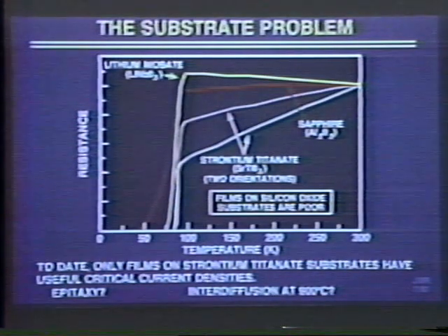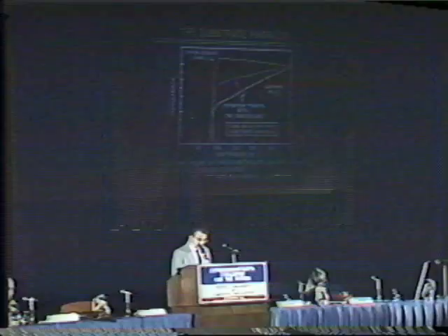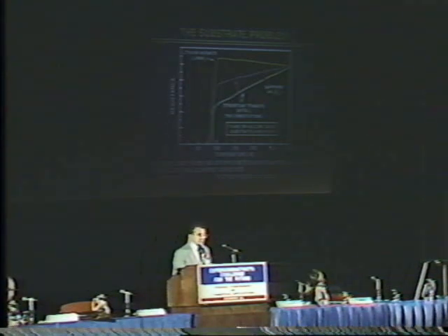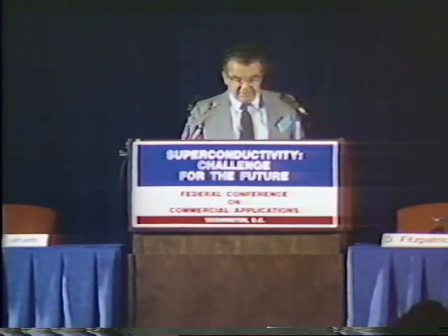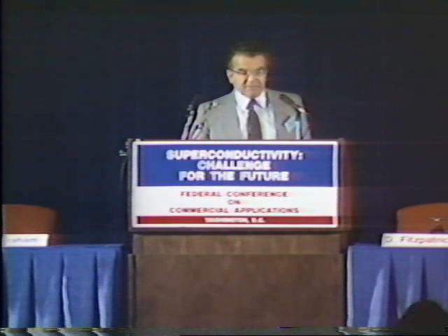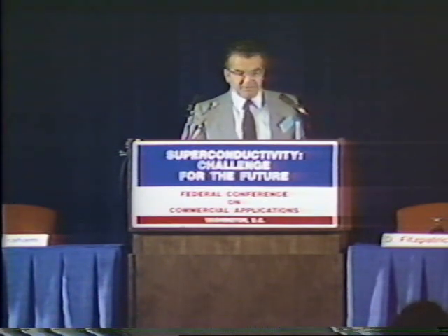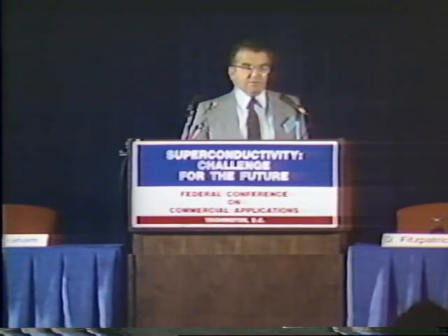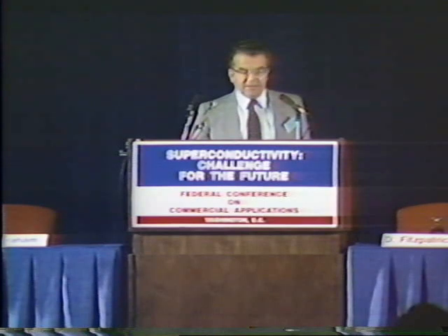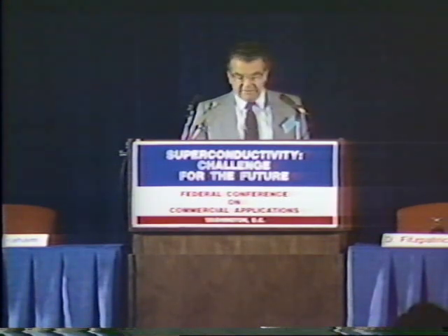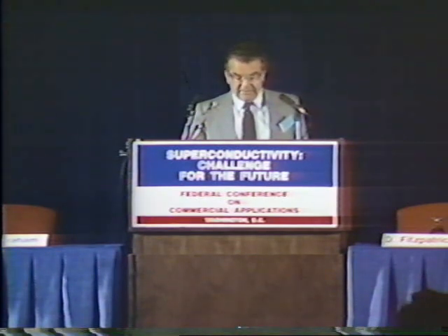To date, as far as I know, only films on strontium titanate substrates have useful critical current densities, in other words, 10 to the 5 amps per square centimeter or more at 77K. If anybody has any other information, they can tell me afterwards. There's one particular orientation of strontium titanate that seems to be particularly useful, and there's speculation that two effects are going on, or we know that two effects are going on. One is epitaxy, or at least a limited amount of epitaxy between the film and the substrate, the matching of the crystal structure. And the other is that there's some interdiffusion at this 900 degree heating step between the substrate and the film, and the interdiffusion with strontium titanate seems to be relatively benign compared to the other substrates that we've used, and I think that's a fairly common experience.